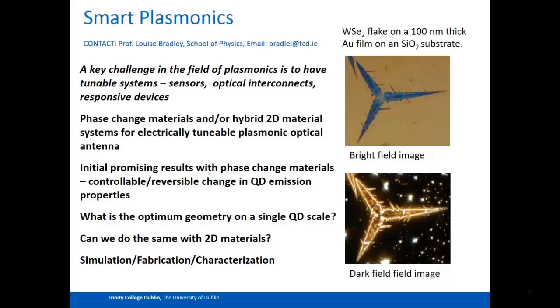Just to give you a flavor of what we do, we do the simulation of the structures using finite difference time domain theory or using finite element theory. So for people who are interested in simulation, we have projects that are suited to you. We do the fabrication using things like E-beam lithography, but we also use chemical synthesis techniques to fabricate tiny metallic structures with particular properties. We use nanoscale emitters such as quantum dots, which we source from people in chemistry, or we use 2D materials. Here's an example of a 2D material which we've characterized in our lab, which has come from Niall McAvoy over in chemistry.